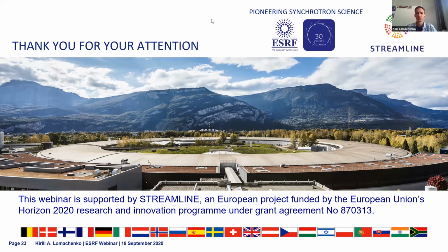From the XAS point of view, XAS does not care whether the samples are in solution, solid, or even in gas. The limiting factor is the concentration of the absorbing species. So it's absolutely no problem if you want to measure in solution, as long as the concentration of the absorbing species is compatible with the data quality you want to get. Actually, liquids are very nice samples for us because very good XAS data quality can only be obtained for quite homogeneous samples - the higher the degree of homogeneity, the better the data quality.